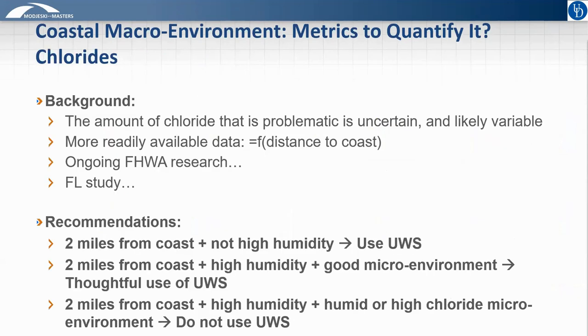What that level of chloride is difficult to precisely determine, but what is easier to analyze is the performance as a function of distance to the coast, which can be indirectly related to chloride concentrations. This is the approach being implemented in the ongoing FHWA study on this topic, but the best available data on this metric at the present time comes from a study by Rich Granada focused on performance in Florida, where 2 miles from the coast was viewed as a reasonable threshold for where uncoated weathering steel could be used with confidence.